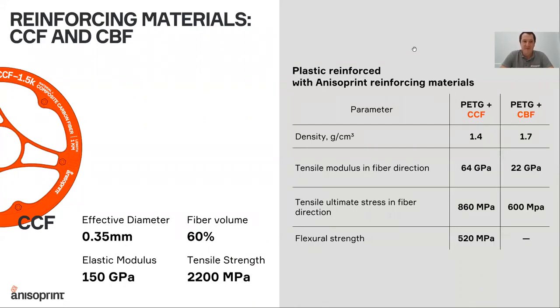So this stiff filament, if we're talking about the carbon, the CCF, is a very thin and very stiff fiber, which has a round cross section and an effective diameter of about 350 micron. It has about 60% pure fiber by volume, and about 40% by volume of special resin matrix. The mechanical properties of the fiber itself are very high. The elastic modulus of this material is more than 150 GPa, and the tensile strength is over 2 GPa. So it's many times stronger than steel and all other metals.